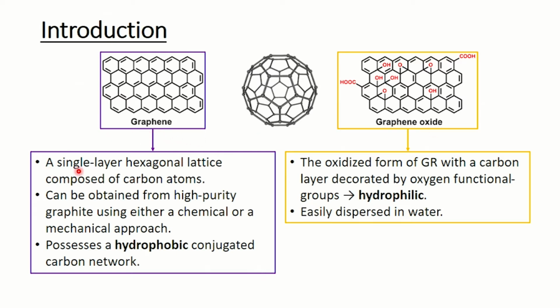Graphene, a single-layered hexagonal lattice composed of carbon atoms, is the simplest form of the carbon layer and the thinnest material produced up to now. With a typical thickness of 0.32 nanometers, a single or few-layered graphene can be obtained from high-purity graphite using either a chemical or a mechanical approach.